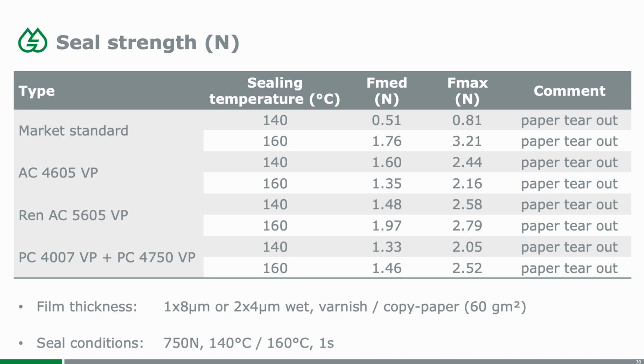But if you see the comment on the right hand side, you see that in all cases we get paper tear out, so it's not that the seal bond is breaking, it's actually the paper which is failing. And all products have, let's say, similar heat seal performance, all Alberdingk products I should say, whereas the market standard at the two different temperatures performs very, very differently. At low temperature you have nearly no seal force, but then at the higher temperature you get a pretty high seal force. But we are working on trying to find better equipment and try to produce more representative data. But nevertheless, all these products can be sealed without issues.